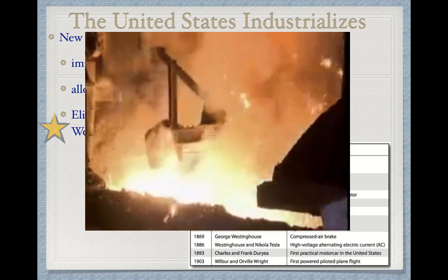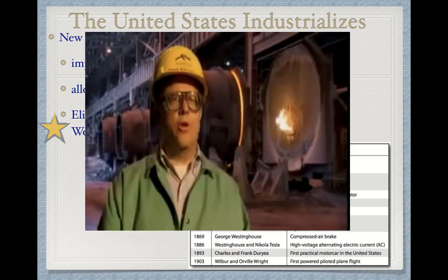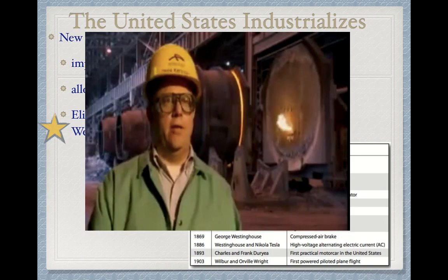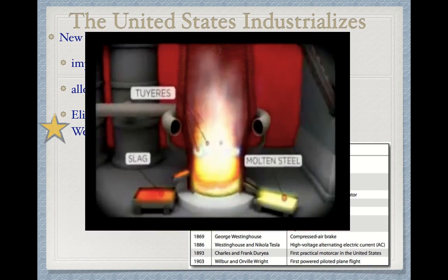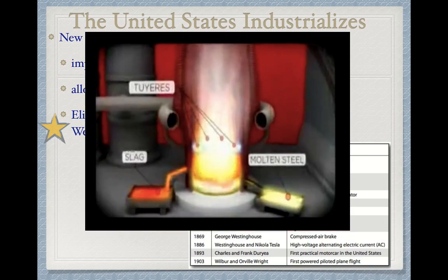The molten steel ignites the oxygen, only this time the fuel isn't coke. It's the actual carbon atoms bonded to the iron. Basically, the molten material itself is burning. We flow 25,000 cubic feet of oxygen per minute into the bath in the vessel. The oxygen reacts with the carbon and reduces the carbon level. The longer and hotter it burns, the more the carbon burns away.